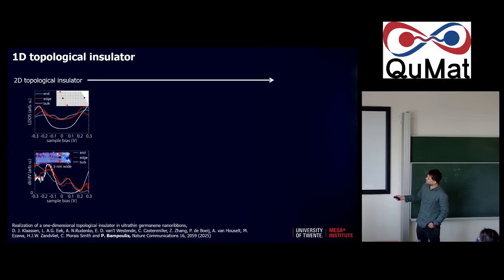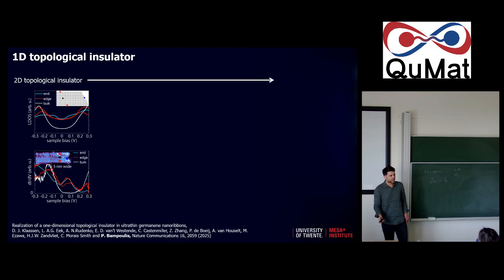On top here is the theory of the local density of states. At the bottom here is the DIV over the sample bias, something that is proportional to the local density of states. And what you see with red over there is the top. This is the nanoribbon over there, the top and the bottom edge. White is the middle of the nanoribbon, and light blue is at the end of the nanoribbon. This is a very wide nanoribbon, about 5 nanometers, so you see essentially that the edge state runs around the nanoribbon, and there is not much difference between the two edges of the end.